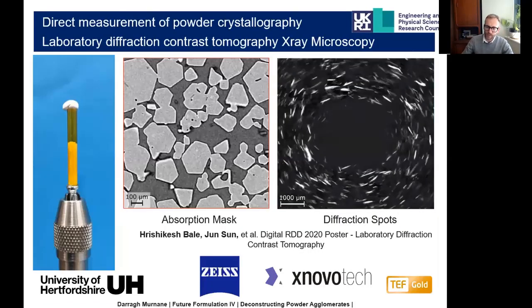So work which we're just about to publish, but we've published some of the preliminary findings again at the RDD conference just a month ago, is to carry out a laboratory diffraction contrast tomography approach. So we can see some of this first work that we've undertaken here. We've got a Kapton tube that contains crystallized hexamine, which our colleagues up at Leeds very carefully controlled the crystallization approach. We can see just a two-dimensional slice through one particular plane of that sample here, showing the individual crystals of hexamine.